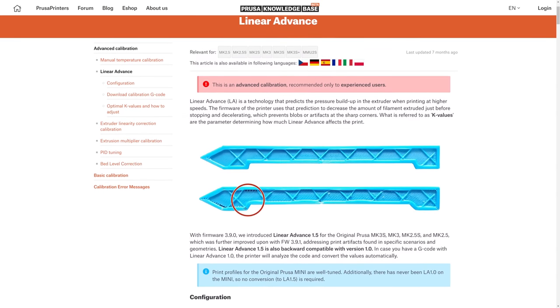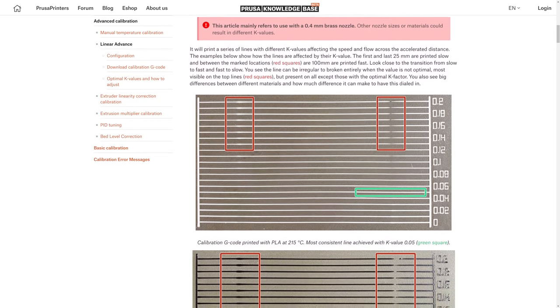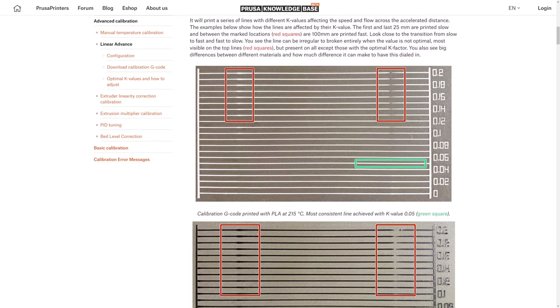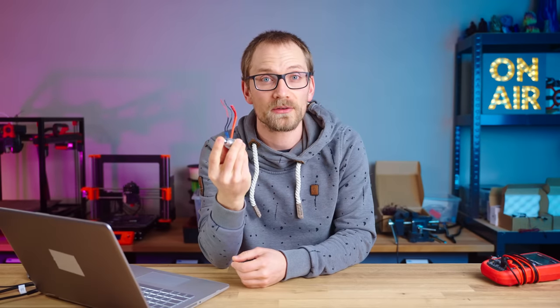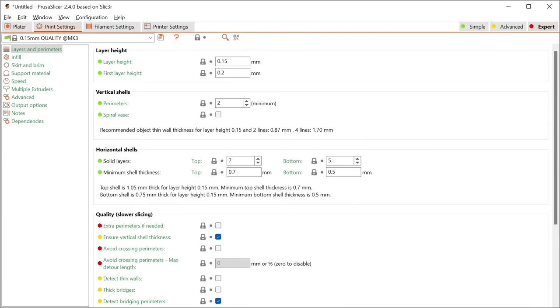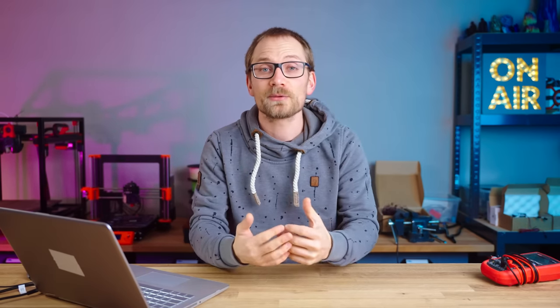So what can you do? Many modern printers have pressure advance enabled and tuned in their firmware, which tries to counteract that laziness in hotend flow characteristics. But it is tuned for the factory setup, so with a different nozzle or hotend, or with a worn-out or loose filament path, it's not going to work that well anymore. Check that there's nothing worn out. If your printer does not use pressure advance, simply setting the feed rates for the inner and outer perimeters to the same value should take care of the issue. Going slow and keeping the hotend and extruder at a constant steady state is usually the safer bet for maximum consistency and quality.